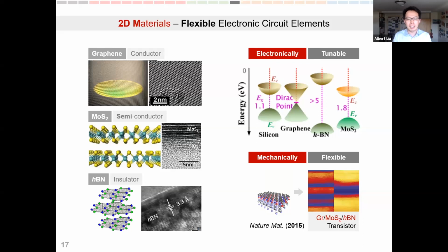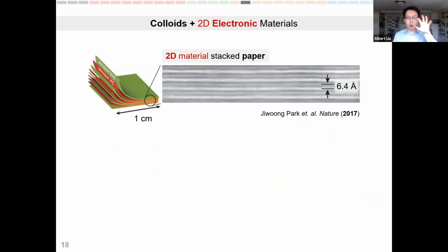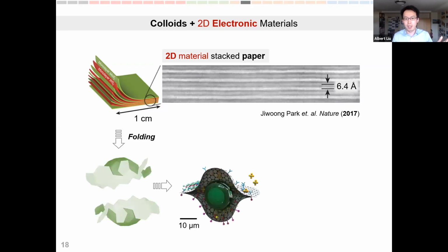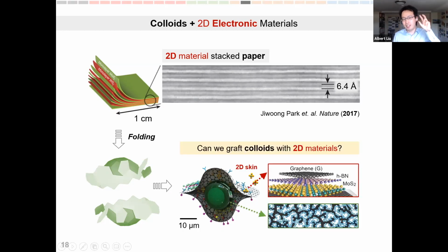So here comes the idea. You take a colloidal particle, and treat the 2D material as origami paper. So you can pre-pattern electronic circuitry within the two-dimensional materials with different composition. And then we fold these two-dimensional materials around a dumb colloidal particle in the middle, making these microscopic dumplings that have two-dimensional material covering their surfaces. These dumplings, or raviolis, depending on where in the world you come from, basically have an electronic skin and a polymeric support in the middle.